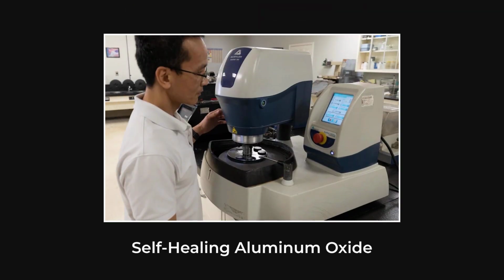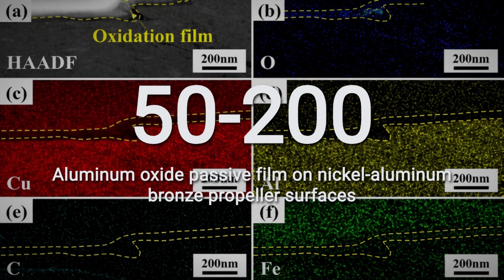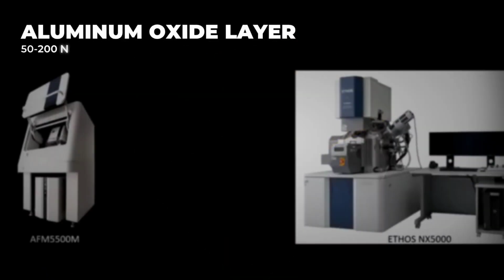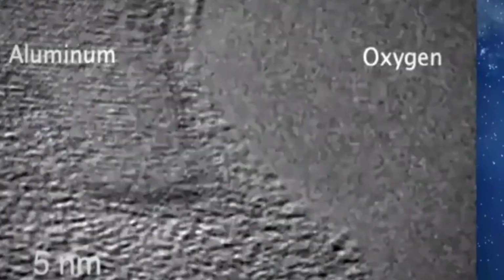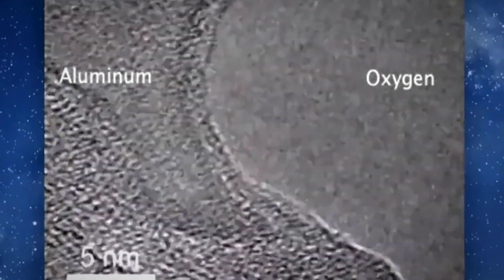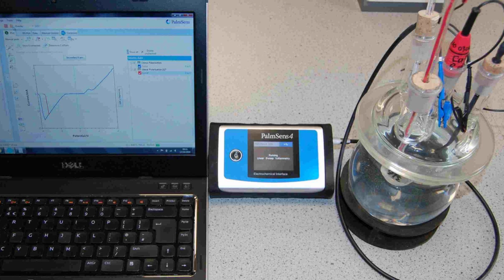Instead of decaying, when exposed to salt water, the aluminum within the bronze reacts instantly with dissolved oxygen. This rapid reaction creates a dense, non-porous, passive oxide film, primarily composed of aluminum oxide, measuring just 50 to 200 nanometers thick. To put that in perspective, this molecular protective barrier is roughly the thickness of a single sheet of household plastic wrap. If sand, debris, or cavitation bubbles physically scrape this film away, the exposed aluminum instantly reoxidizes. It is a completely self-healing system that continuously seals the metal against further dissolution.